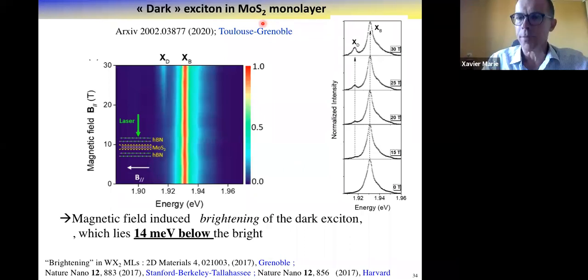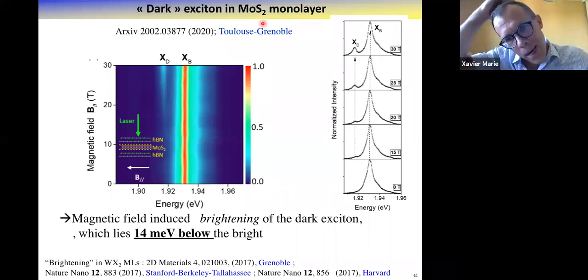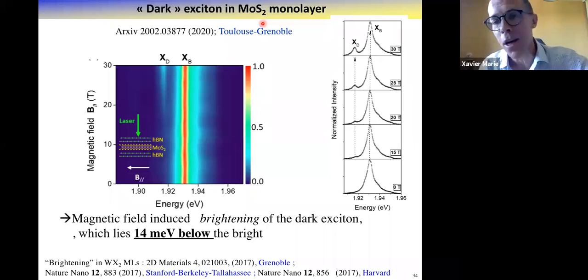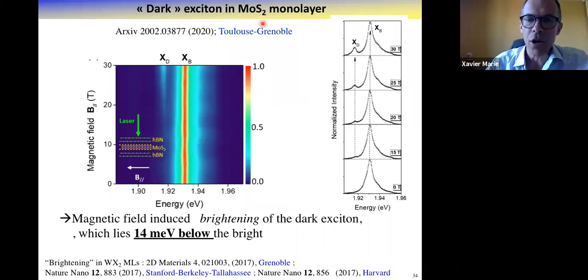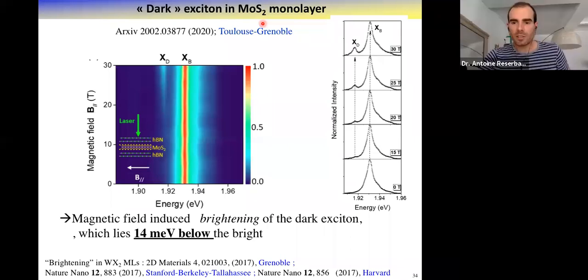And on MoSe2, it lies 1.5 millielectron volt just above the bright exciton. So the mixing is induced at much weaker magnetic field. And with this, with a more standard magneto photoluminescence setup with 9 Tesla, where we can do time resolved measurements, indeed we should observe this effect of increase of lifetime due to the mixing of states. Yes. So there are a lot of questions.